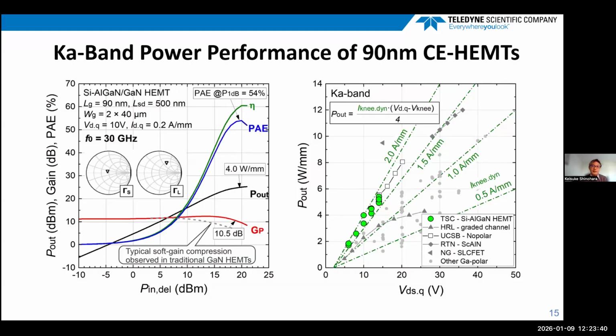And on the right, the obtained output power density is plotted as a function of quiescent drain bias. The slope of this linear line represents the effective dynamic knee current density. Our data shows a knee current density of about 1.9 amps per millimeter, which is consistent with the DC knee current density all the way up to 15 volts, which means that the device is not experiencing severe current collapse up to such a high voltage and high power density.